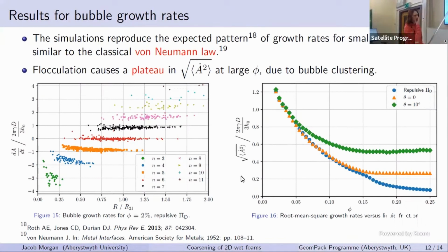I think it's interesting that for the repulsive case as compared to the 0 contact angle case, which perhaps confusingly does include adhesion as a result of our finite film thickness, in the sense that if one brings a pair of liquid-gas interfaces together to form a film, for the contact angle to be 0, the film tension must equal twice the isolated interface tension, and so the total work done in bringing those two together must be 0.